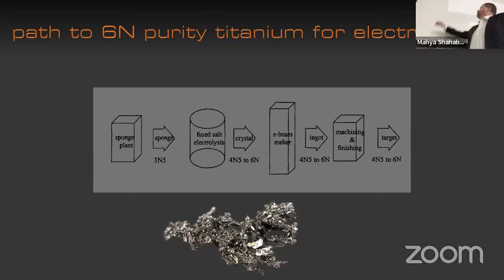We're working from a sponge plant. Typically, a lot of people make primary titanium with the Kroll process. We actually use the sodium process, the Hunter process, instead. And you get a reasonable amount of purification even at that step, because the TiCl4 is reasonably purified. But you get some sponge. We ship it from Utah to Pennsylvania, near Pittsburgh.